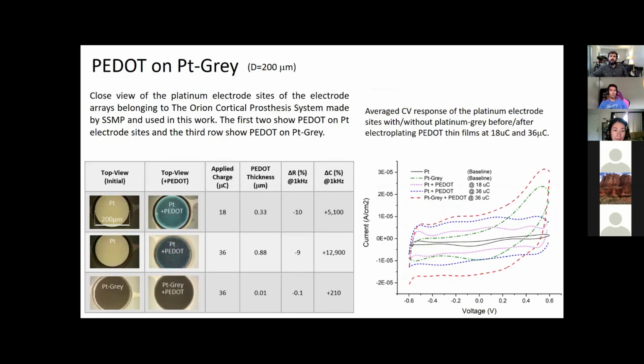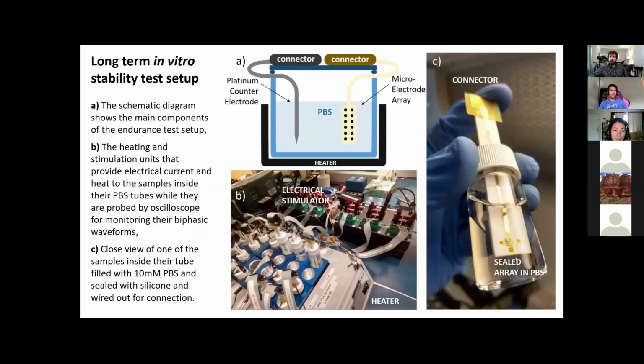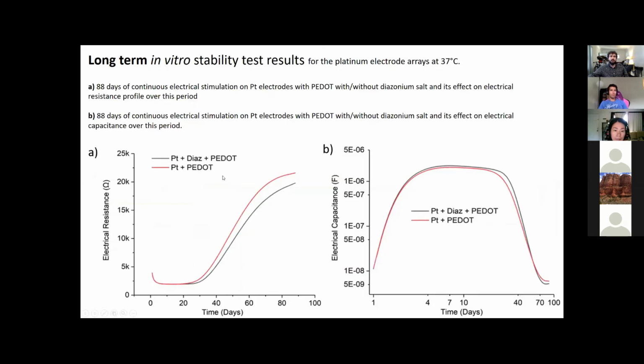So I ran long-term tests, and I realized, yes, when you have platinum PEDOT, diazonium salt chemically helps to have less of an increase in electrical resistance over time. And also, when you have diazonium, your capacitance, which is improved already from here to here after you plate it, drops a little slower than when you don't have diazonium salt.